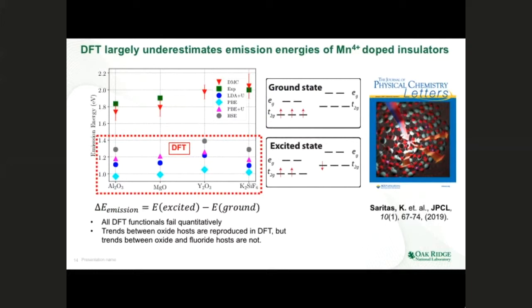And for some of the structures in here, especially for aluminum oxide, I needed to simulate up to nearly 80 atoms in order to make sure that I have a converged simulation cell. What we see in here is that the red results are the DMC results with the error bars, and the green squares are the experimental emission energies. The rest of the results are for the DFT calculations, where the blue ones are LDA plus U, the cyan ones are PBE, pink ones are PBE plus U, and gray ones are HSE. We are not really seeing too much improvement as we go from LDA to PBE plus U. So this was really interesting as a demonstration of the failures of DFT. And I would also like to mention that this work was also featured in the JPCL.